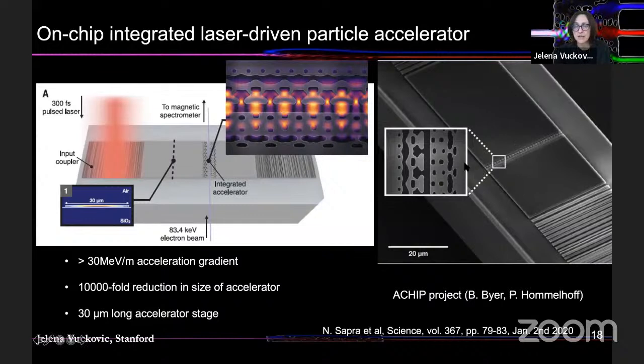It's made in silicon. Again, the patterns that I showed you before. It also has these inverse design couplers because we also have to couple light from very powerful lasers, which are very short and energetic broadband pulses. So there are also couplers that don't really exist readily in photonics that we had to optimize here. And we did the experiment where we couple electrons to this vacuum channel with initial energy of 83.4 kilo electron volts, and we look at what happens at the output when we turn the laser on or off.